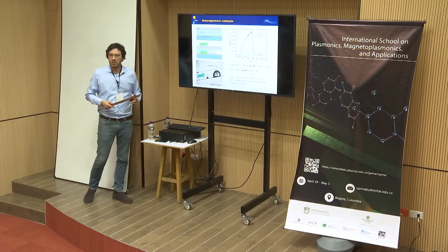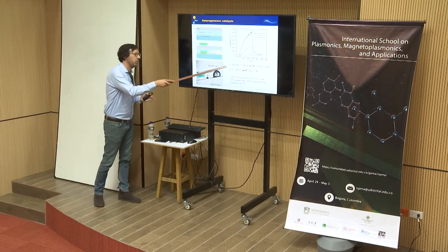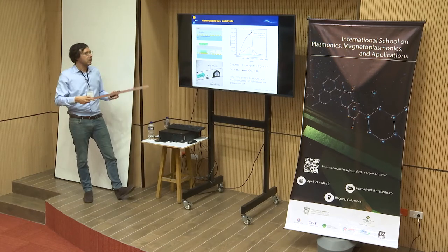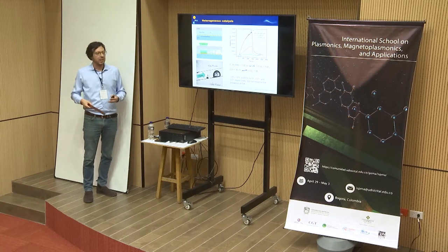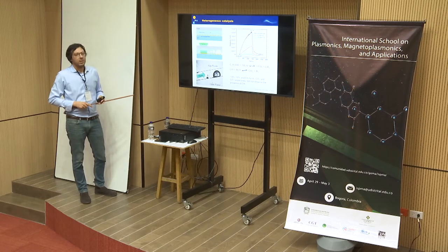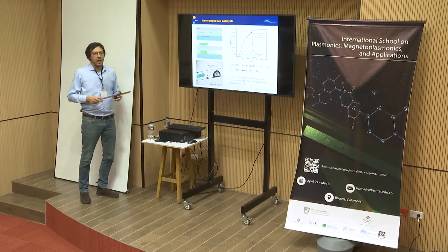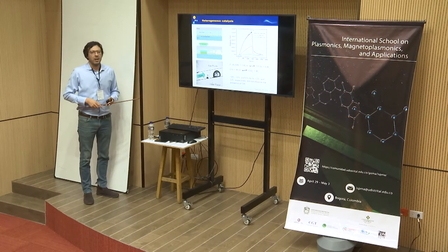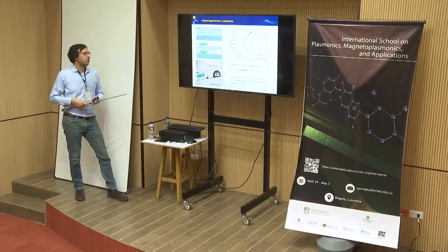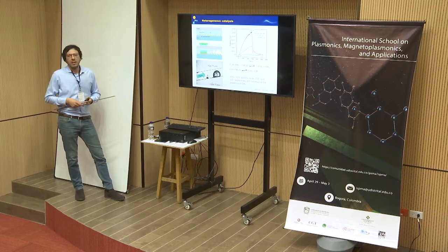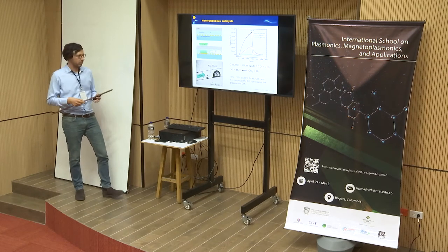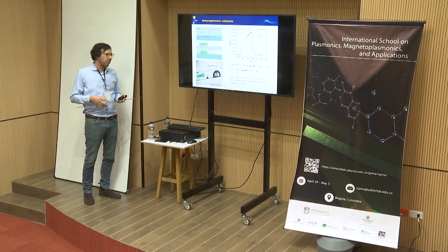To detect the products, and what they saw was that they were able to create basically carbon dioxide and hydrogen. So they were able to drive heterogeneous catalysis in situ, the photoreforming process of methanol, by just shining the light. Usually this process really happens at high temperature, like 300, 400 degrees C. So this was really the proof that we could drive a heterogeneous catalytic process by just using a light source and a metal nanoparticle. So this was very important and triggered a lot of interest in my field, for example.